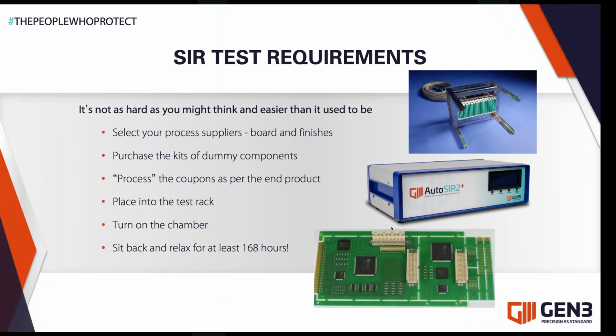It's not as hard as you might think, and certainly easier than it used to be. So when you want to consider these aspects, you want to select your process suppliers, what board and what finishes you're going to have. You need to purchase the kits of dummy components, then process the coupons as per the end product, then place it into the test rack, which is highlighted here. This is an example of a test rack that we make. Put that into the environmental test chamber, get it up to temperature, and then sit back and relax for a week whilst the test runs. So that's a very simple way of what you need to do when running SIR.